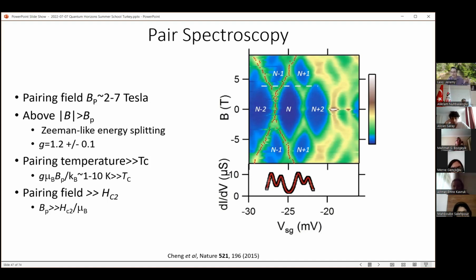So instead of going n-2, n-1, and so forth, it jumps by 2 at a time. If you were to apply a sufficiently larger magnetic field, then you could get to a regime where there was n-1 or n+1. And so this is a critical field at which the electron pairs break up. And it turns out that electron pairing is an ingredient in superconductivity. So you need, of course, phase coherence between the electron pairs, and it's a macroscopic quantum state.